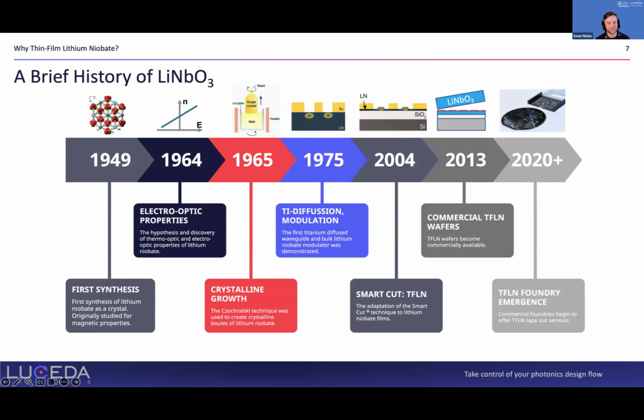So what is the history of lithium niobate, and how did we arrive where we are today? It actually goes back pretty far. 1949 was the first synthesis in a lab of lithium niobate as a crystal. At that time, they didn't know that it would become a great photonic material for thin film devices. This was purely the first breakthrough and where we made lithium niobate. It actually took until about the 70s to become used in modulation at all. And at this point, they started to diffuse titanium into the lithium niobate to form waveguides. So we'll talk about this more in just a second, but this was really the start of lithium niobate for modulation. And this is what we would call bulk lithium niobate.